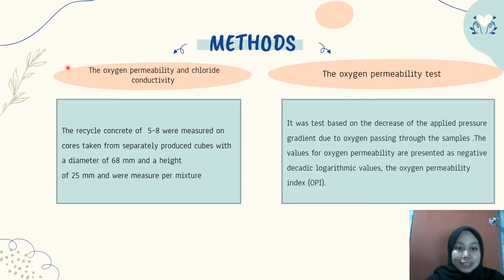Then the method used is the oxygen permeability and chloride conductivity, where the recycled concrete of 5 to 8 mm were measured on cores taken from separately produced cubes with a diameter of 68 mm and a height of 25 mm, and were measured per mixture. Then the oxygen permeability test was tested based on the decrease of the applied pressure gradient due to oxygen passing through the samples. The values for oxygen permeability are presented as negative decadic logarithmic values. The oxygen permeability index, which is OPI.